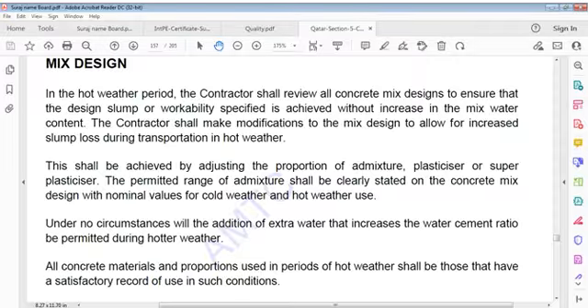This shall be achieved by adjusting proportion of admixture, plasticizer or super plasticizer. Permitted range of admixture shall be clearly stated on concrete mix design with nominal values for cold weather and hot weather use. Under no circumstances shall addition of extra water that increases water cement ratio be permitted during hotter weather.